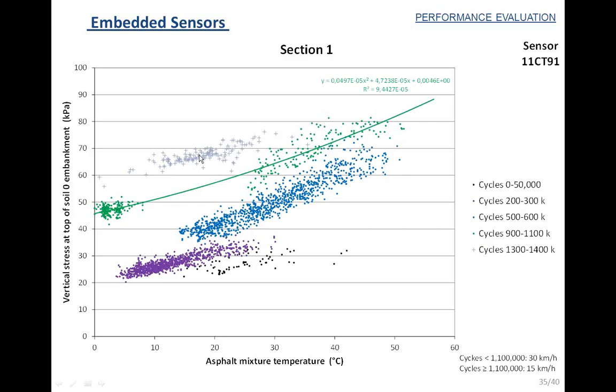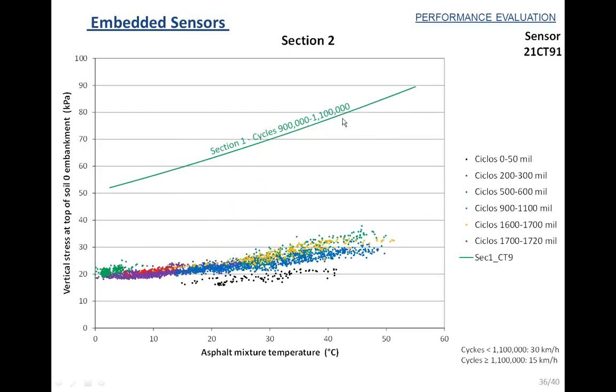And these additional points correspond to cycle 1.3 million. So we draw this green line that we wanted to have as a reference in order to compare to the other sections. Remember that this line is representative of a fully flexible pavement with a high level of deterioration of the asphalt mixture. This increase in the stress level is mainly due to the deterioration of the asphalt mixture. So this is the information from section number 1, and of course for section number 2 the stress level was very low.